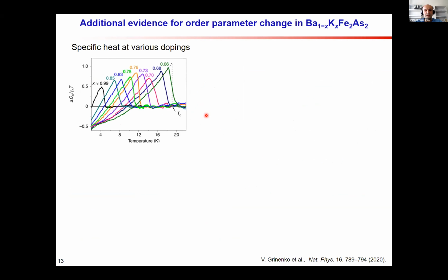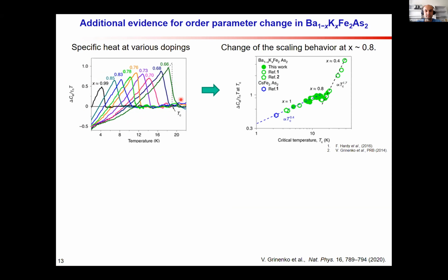So of course, it's important to search for other indications of this unconventional superconductivity and a change of the pairing symmetry in this doping range. Here I would like to show how the specific heat changes across this doping level. This is the temperature dependence of specific heat for different doping levels in the superconducting state. If we plot the specific heat jump at TC, normalized by the Sommerfeld coefficient and by temperature, we found that there are two characteristic scaling behaviors.